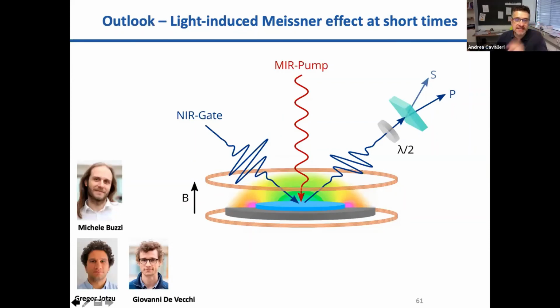Let me say two things. What we're trying to do is to show that if you take a material and you can measure optically the magnetic field expelled from the material before and after photoexcitation, you should be able to see this. We've been very good at destroying superconductivity. We have not been that good yet at detecting the Meissner effect, but this has to do with, if you're familiar with the difference between in-field cooling and zero-field cooling, a complicated protocol: pumping a material many, many times reduces the effect by several orders of magnitude, because you'd generally be observing in-field cooling, which is of course much lower than the zero-field cooling effect, although some will say that is the only real Meissner effect that one should be looking for.